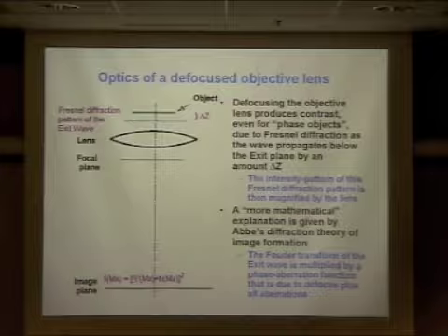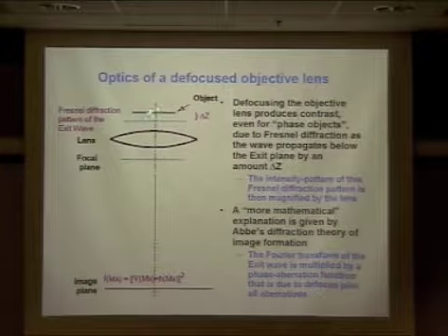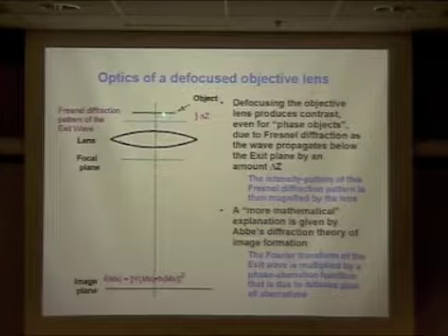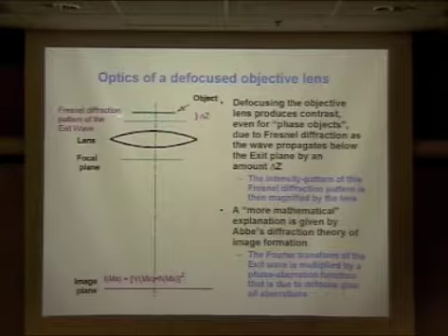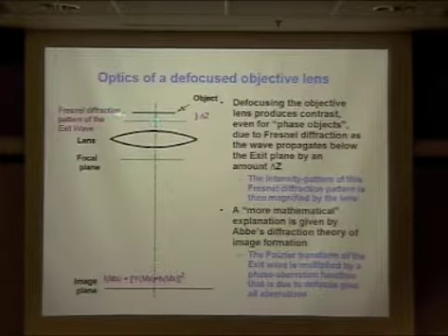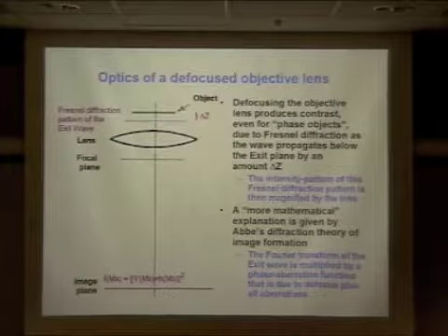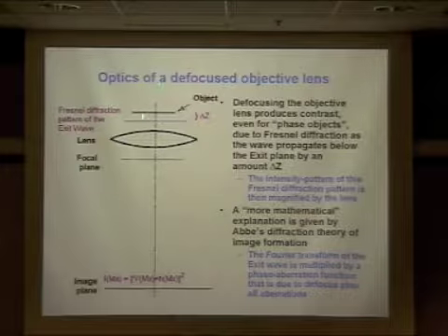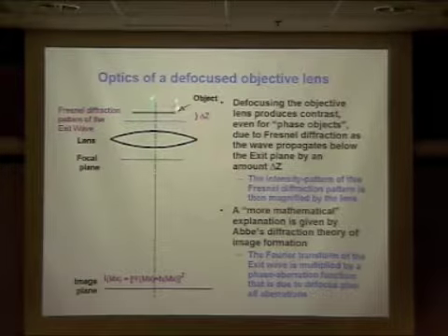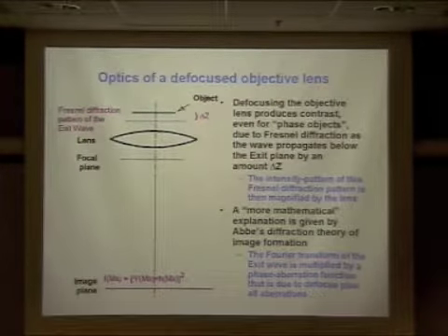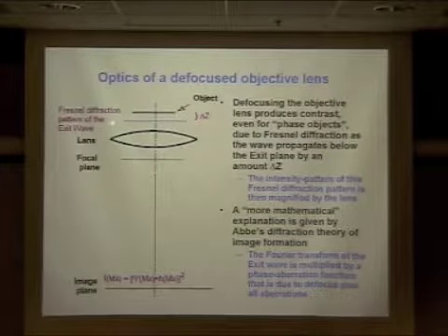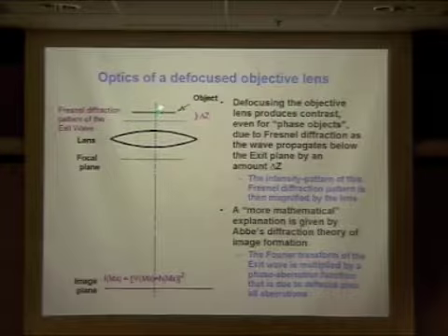The simple way is to say that if we have a transparent object, a phase object, there are no amplitude variations in the exit wave, but there may be variations in the phase, because electrons going through one part have experienced one refractive index and then going through another part have experienced some other refractive index. And so the phase is varying, but there's constant intensity.